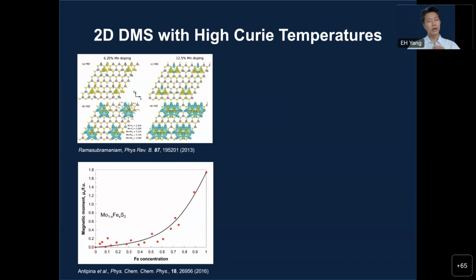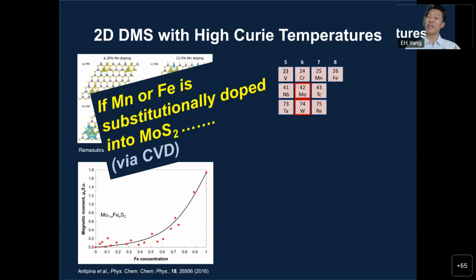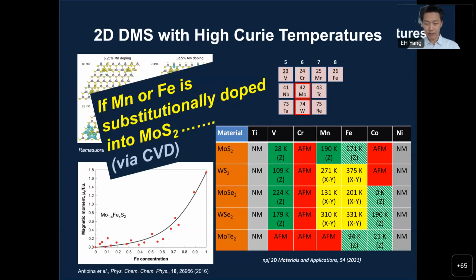Okay. Our work was motivated by a couple of theory papers that claim that if manganese or iron atoms are substitutionally doped into molybdenum disulfide monolayers, then one will see room temperature ferromagnetism. That was the claim given by these two theory papers. And then more recently, in 2021, another theory paper anticipated ferromagnetism here, in this yellow part, and room temperature or close to room temperature ferromagnetism from tungsten disulfide, molybdenum diselenide, and tungsten diselenide, if manganese or iron atoms are doped. All right.